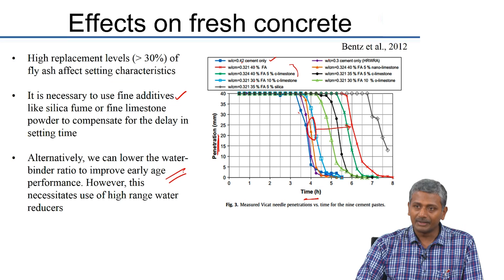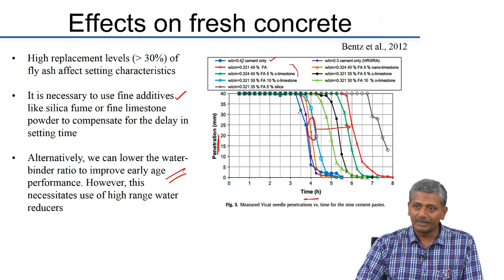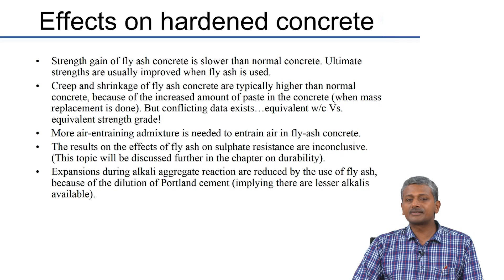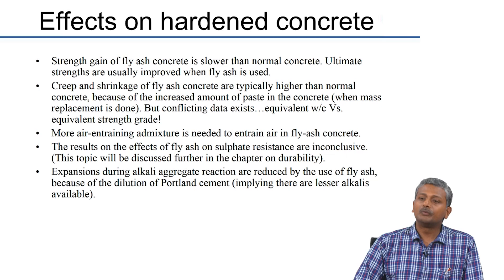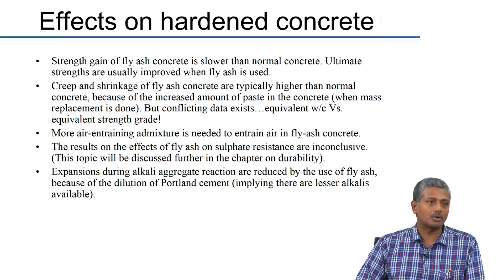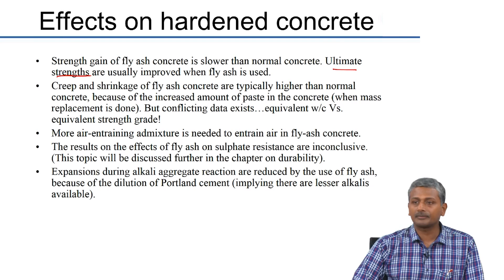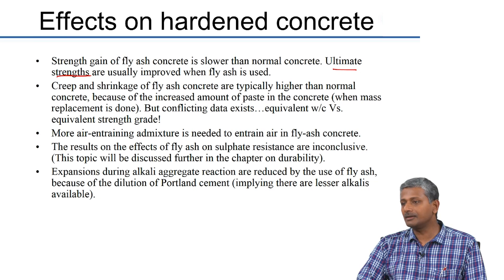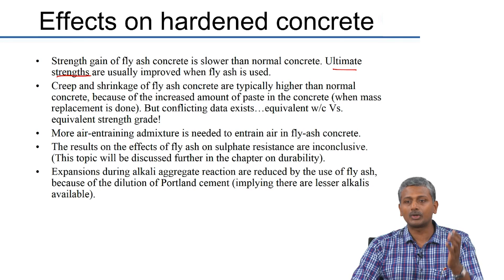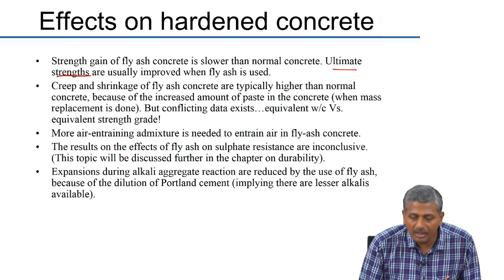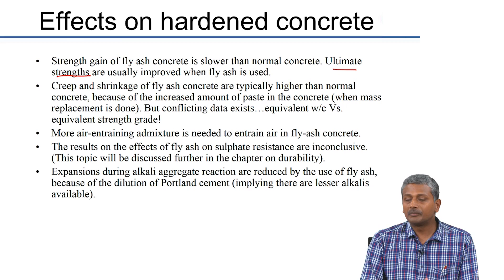As far as hardened concrete is concerned, we expect a delay in strength gain characteristics. With type F fly ash at 20 to 30% replacement, it will take nearly 14 to 28 days to achieve similar strength as plain concrete. But if curing continues for a long period — 56 days, 90 days, up to 1 year — ultimate strengths can be significantly improved compared to plain cement because fly ash reaction continues as long as lime is available from the cement system. Creep and shrinkage are generally higher primarily when mass replacement is done.